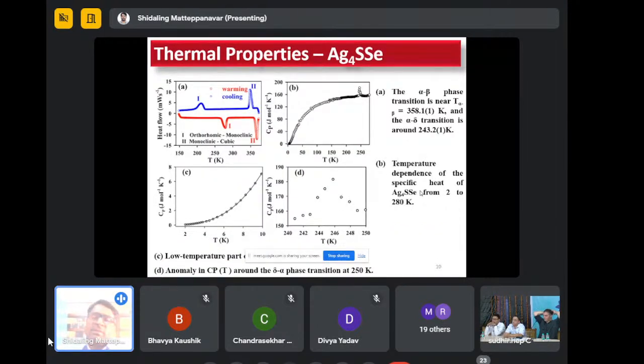And these are the thermal properties we have studied. So we have seen all the structural transitions here. The first, blue line shows one around 350K, which is due to the cubic to monoclinic transition, and one from the monoclinic to orthorhombic. The red one shows monoclinic to cubic, and this is the second transition.